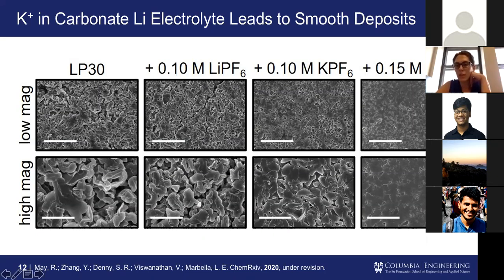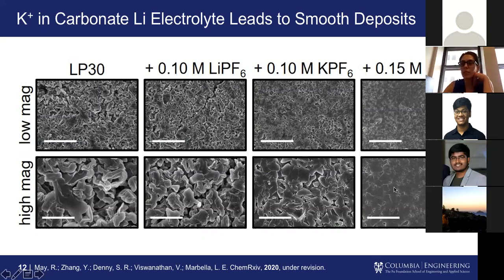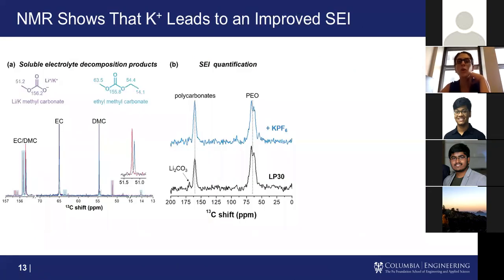Still some high surface area structures in here. But if we add 0.15 molar, we end up getting these large areas of smooth lithium deposition that are much more favorable and more safe for the battery. So this tells us that something is happening to the electrolyte decomposition at this concentration of KPF6 that mitigates lithium microstructural growth. So what's actually going on here?